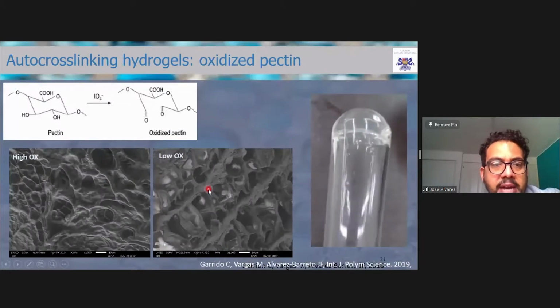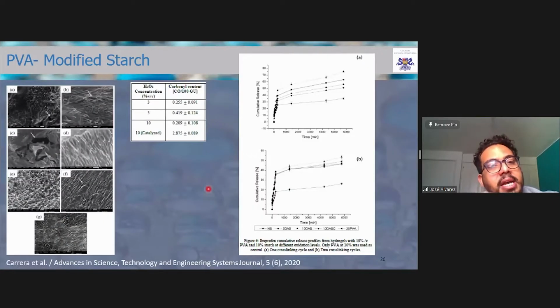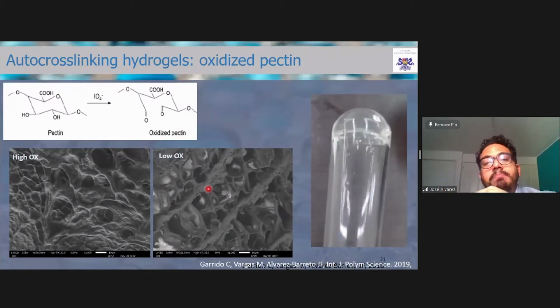Then after that, we went and looked at the oxidation method, but not this time with starch. We looked into pectin, this polygalacturonic acid that we find in fruits, especially fruit peels. We did the oxidation of pectin, this time using sodium periodate, and we used high and low oxidation degrees of the pectins. Here you can see scanning electron micrographs of the hydrogels that we formed.